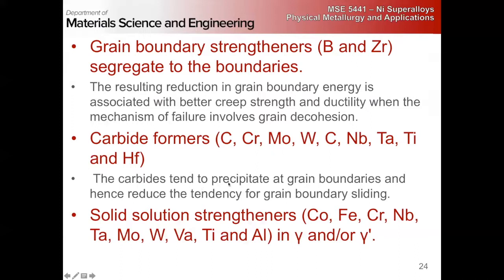These carbides are going to precipitate at grain boundaries and give us a tortuous or serpentine-like grain boundary structure that's going to reduce the tendency for grain boundary sliding at high temperatures, so take away a creep mechanism. And then we have a whole mess of solid solution strengtheners in the gamma or the gamma prime, depending on where they end up. Okay.